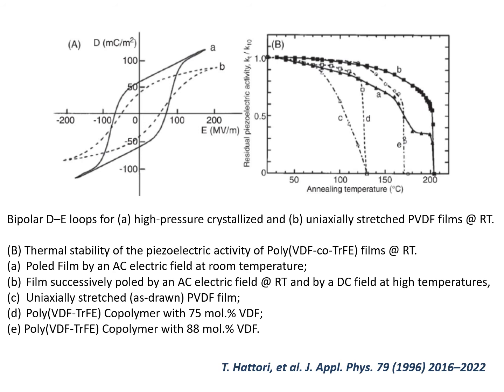And the same group also investigated the thermal stability and also the residual piezoelectric activity here. So you can see that, according to the conditions used, for instance, when your film is poled with an AC electrical field at room temperature, and then a direct current field at high temperature, you can have some different behavior. So this is the piezoelectric activity versus annealing temperature. Of course, the film has to be annealed in order to enhance the properties.